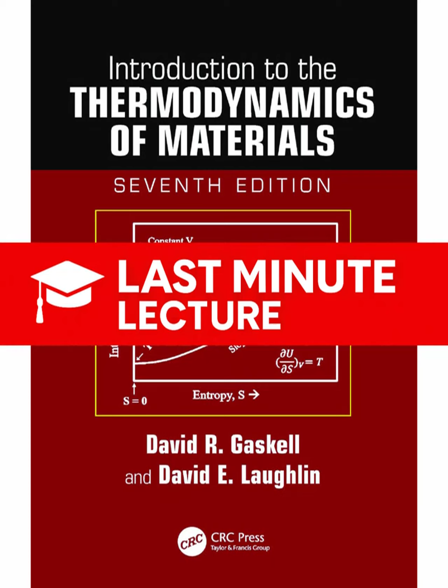The entropy of the gamma phase has to be larger than the entropy of the alpha phase. And this is totally counterintuitive because the FCC is a more closely packed structure. You'd think it would be more ordered. That seems to challenge the simple idea that entropy is just about crystal structure, so what's really going on?